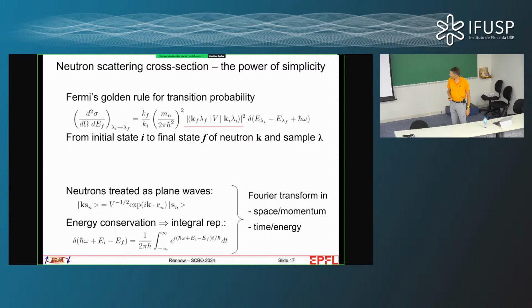Okay? So why is neutron scattering so great? Well, the reason why it's so great is that it's very simple. Neutrons interact very weakly with matter, which means that first-order perturbation theory is valid. And so that means that all that we have to do is to take the interaction between the neutron and the sample, and then take the matrix element between the initial state of the sample, the initial state of the neutron, the final state of the sample, and the final state of the neutron.